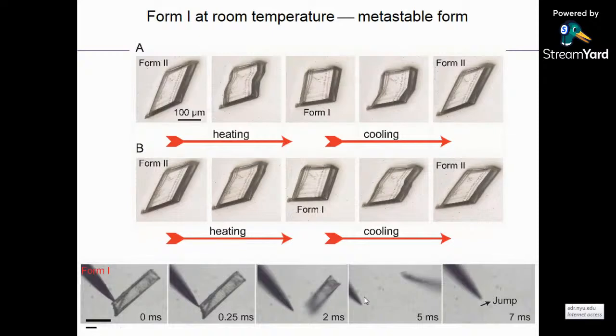Apart from the self-recovery behavior, these crystals are also known for a phenomenon we have identified, known as thermosalient behavior. Let me explain it in simple words. As I said earlier, these form 2 crystals can be heated to form 1 at high temperature, at about 75 degrees centigrade. When you cool to room temperature, they come back to their original shape.